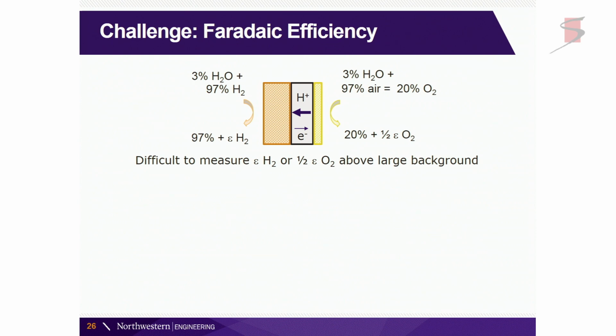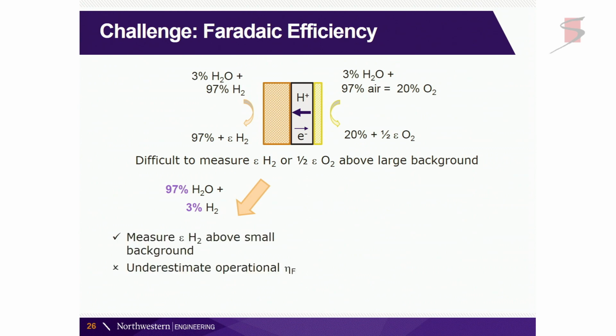You can detect the oxygen that's produced on this side, and that's a little bit easier because it's not quite a high background, but it's still a high background. So you'd say, well, let me reduce the hydrogen amount that I'm supplying to my fuel electrode so that I can measure the hydrogen that's being produced from the electrolysis. The challenge there is that, that works, but you're going to underestimate the Faradaic efficiency because now you've moved into the regime where the electrolyte is actually a little bit more electronically conducting. So you're going to make your numbers look worse than they would be in the more operational condition.